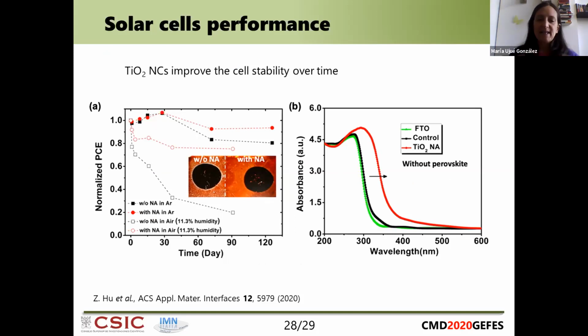Okay, so we measured the absorption of the system without the deposition of the perovskite, the absorption of the coating, the titanium nanostructure and non-nanostructure. Let me see if I am able to do this. Yes, this will be the FTO and this will be the control. The control is the compact titanium layer. So you see that we have a strong absorption here, I mean there is a lot of light going through in this UV region. But when we put the nanocolumns there, this absorption is shifted. And we think that the fact that we are limiting the absorption of this light is somehow protecting the perovskite from degradation.